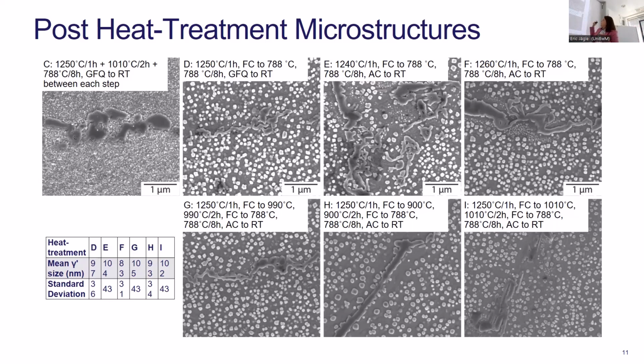So we see the carbides precipitating in very similar structures. We don't see a huge difference in morphology for the carbide species, but the carbide species are M23C6 and M6C. We don't see anything else coming out in any of them. The key difference that we see is the tertiary gamma prime.